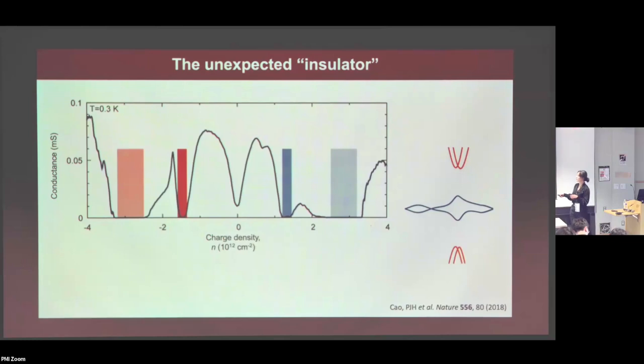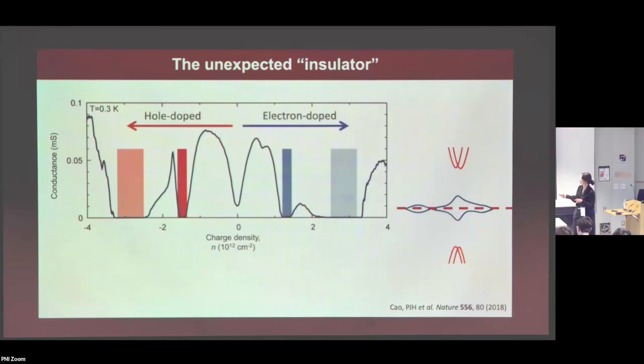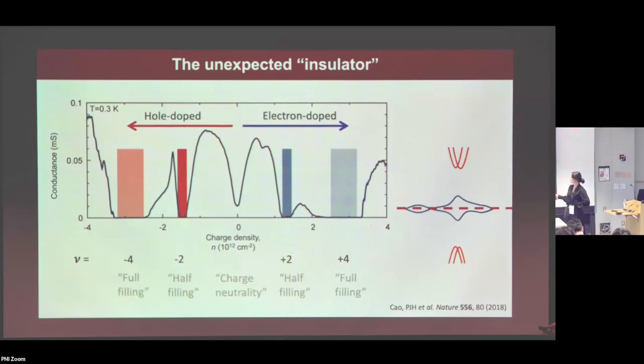Okay, so just to orient you once more in this context, here's the conductance plot as a function of charge density. And once again, this 0 is called the charge neutrality point, which is the level in between the 2 flat bands. Then as you go to the right side or the left side, it means you electron dope or hole dope, meaning you fill up the upper flat band or the lower flat band. And then there's this nomenclature that we use called the filling factor, which ranges from 0 to ±4 in this particular diagram. And that 4 is the same 4 that we talked about in the previous slide with the 4-fold degeneracy of the flavors. So this means that once you reach this ±4, you reach this band edge, okay? So it makes sense that you have this conductance minimum because you literally have a band insulator. So that's called a full filling.